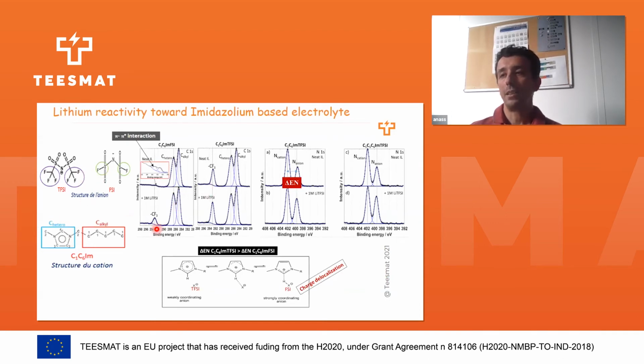When we add, for example, the salt LiTFSI, a new peak appears, which is related to the CF3 group in the TFSI. So here we can see that the carbon peak can give very accurate information about the chemical structure of the materials. That is regarding the carbon peak.